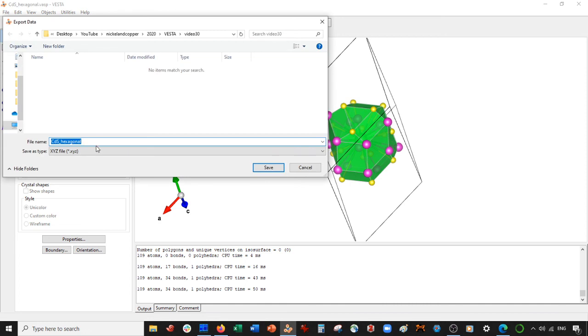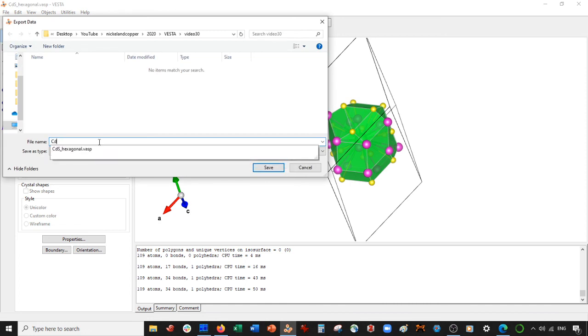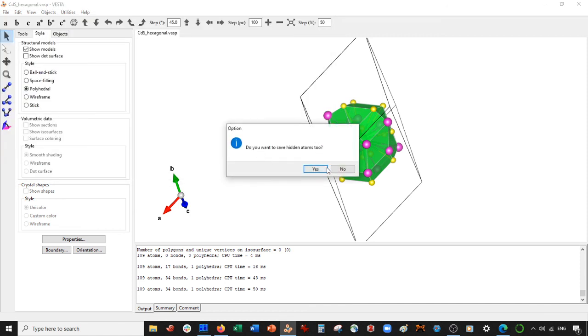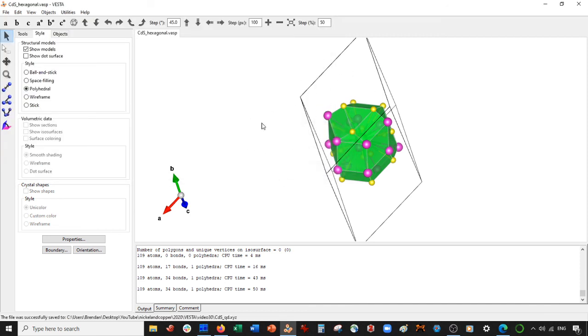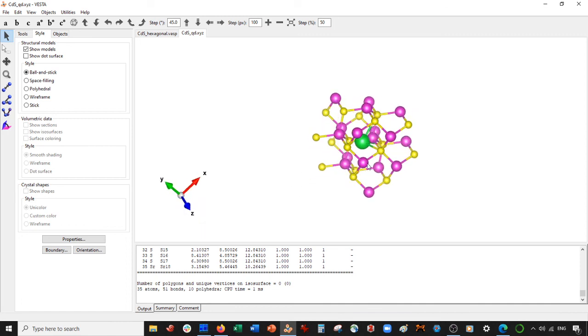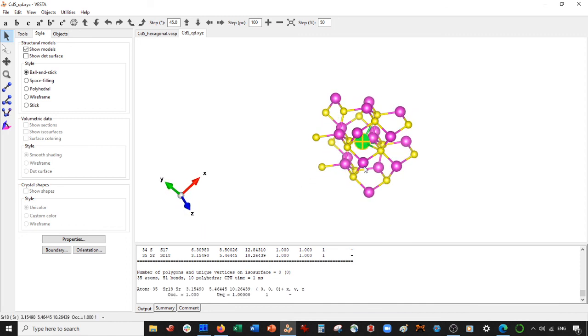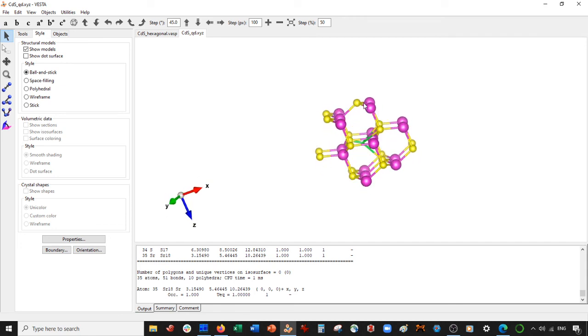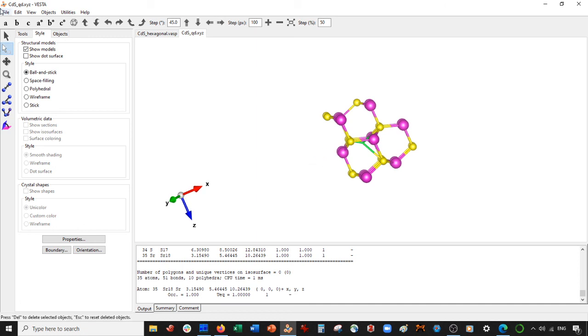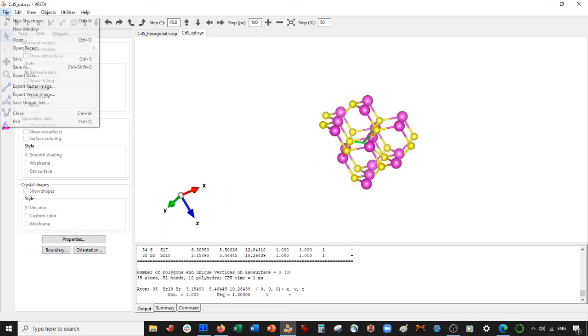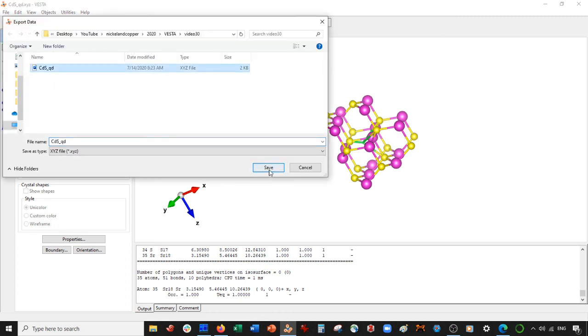Go to File > Export Data and export this as 'CdS_qd.' When saving, do not save the hidden atoms — if you save the hidden atoms it'll save all the atoms you just deleted. Now let's open it up because there's a final step: we have to delete the strontium atom that was in the center, and also delete any non-bonded atoms not part of the cage-like structure. Then we'll overwrite with File > Export Data.